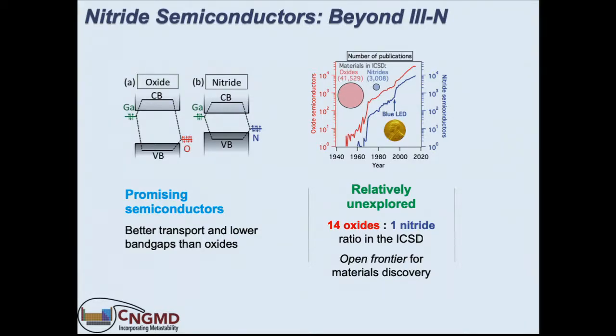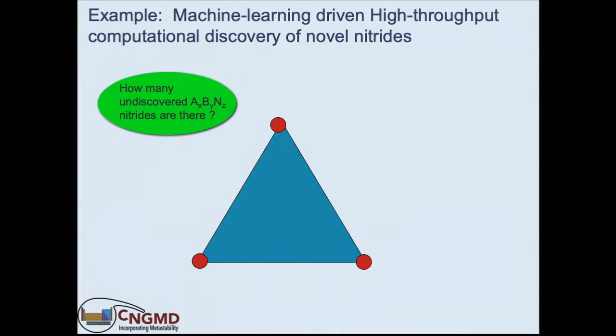This is together with NREL, and we were interested in novel nitride semiconductors because nitrides tend to have lower gaps than oxides, so they're a bit more interesting as absorbers. They are also not as explored as oxides, right? For every one nitride, there are 14 oxides in the ICSD database because people just do a lot more with oxides. So we thought there would be a lot of nitrides you could discover. So we decided to do a giant high throughput search for novel nitrides.